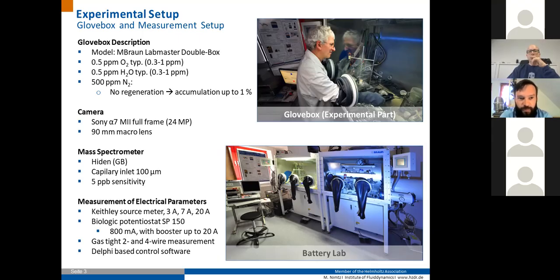This is also a problem for our glove box. This setup doesn't have a regeneration setup for nitrogen, so this means nitrogen will build up when the glove box is operated for longer times, and this leads to several cycles where we have to purge the gas completely with lots of argon to push out the buildup of nitrogen.